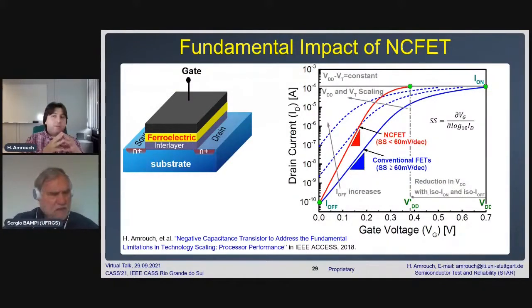Actually, with respect to NCFET, they are getting very good ion. Even some of them showed a 2x improvement on top of the original ion. So this is amazingly good. The problem with the NCFET is how to get the device without hysteresis. And this is not easy because the steepness of the slope makes it really not easy to get hysteresis free. Also, all the underlying physics is still under debate, and whenever you don't fundamentally understand what's happening, it's also difficult.